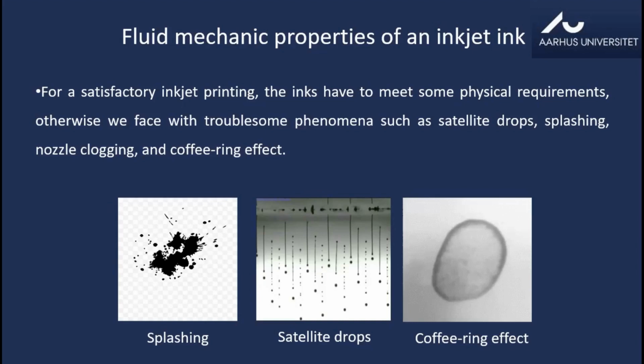So what you will get is, instead of having a very homogeneous line, you will only have particles of silver on the edges, but nothing in the middle. So that would create a problem because you don't have a continuous line in that sense. But there are ways now. A lot of research has been put in, and I think it's a fairly solvable problem if you have the right combination of the inks and the printers. It can be easily solved.